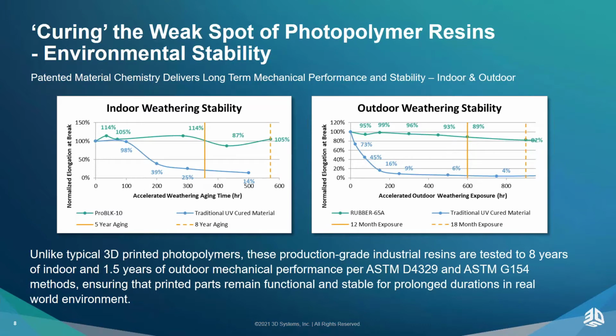And so you see a traditional degradation curve like we see here on the left with a traditional UV cured photopolymer. In this case, we see that the material at just a few years equivalent indoor weathering really drops off and becomes quite brittle, and we lose 75% or more of its elongation within a very short window of time. The unique and novel chemistries that 3D Systems has patented have really allowed us to open up that space for outdoor and indoor weathering and created very nice long-term stability, as shown here in the green curve.